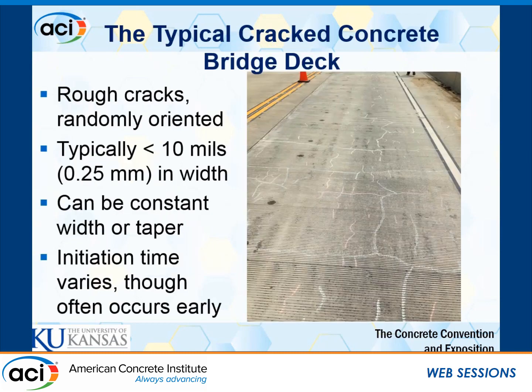KU has looked at a number of bridge decks, a lot in Kansas and even a number of other states across the country. Here's one that's not necessarily doing very well, but relatively representative of what we see. We see a lot of different variations in crack patterns: longitudinal, transverse, map cracking due to plastic shrinkage. Some of the trends that we see for a majority of our bridges, though, is that our crack widths are vastly below 10 mils. We can have average crack widths on our bridge decks range anywhere from as little as 3 mils all the way up to 7 or 8 mils for the ones that have higher crack densities.